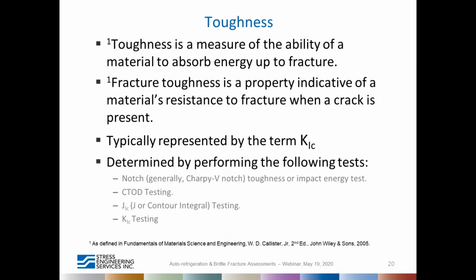So what is toughness? Depending on the level of academic interest, it can be defined in various ways. In general, it represents the resistance to fracture and is measured by the absorbed energy up to the fracture. Fracture toughness, for most of the fracture mechanics analysis involving single-parameter crack driving, is a property indicative of a material's resistance to fracture when a crack is present. However, there is another parameter that's being widely considered and has been researched over several decades. It's called T-stress, which addresses the constraint effect. We're not going to talk about that, although the codes are addressing that at this time.